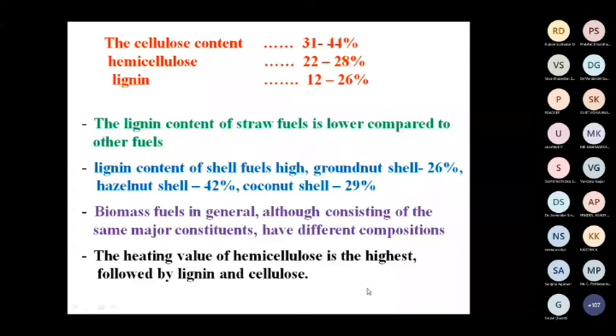So the cellulose content varies from 31 to 44%, hemicellulose 22 to 28%, lignin 12 to 26%. The lignin content of straw fuels is lower compared to other fuels. The lignin content of shell fuels is high, say for groundnut shell 26%. Other reports say hazelnut shell 42%, coconut shell 29%. So lignin content in all the shell biomass is higher. Biomass fuels in general, although consisting of the same major constituents, have some difference in their composition. Heating value of hemicellulose is the highest, followed by lignin and cellulose.